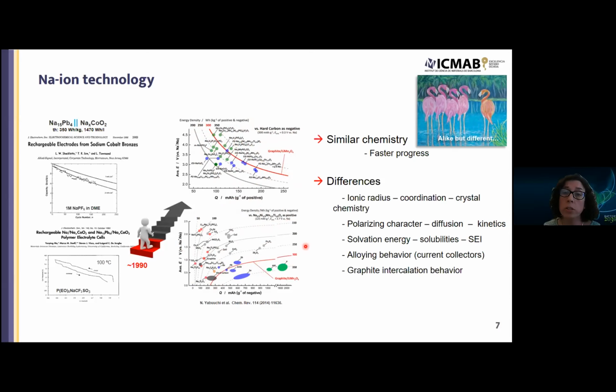So as I was mentioning, this concept has witnessed a fast progress due to the similar chemistry with lithium. But of course, there are also significant differences which need to be taken into account. So there is the ionic radius, which will induce differences in coordination preferences and crystal chemistry. So not all the electrode materials which work for lithium will have a sodium analog which will work as well. Also, the polarizing character, which is due to the higher radius of sodium, is different. So this will affect both diffusion and kinetics. Solvation energy will also be different, and then the solubilities of sodium compounds will be typically higher than for lithium compounds, and this will impact the stability of the SEI.